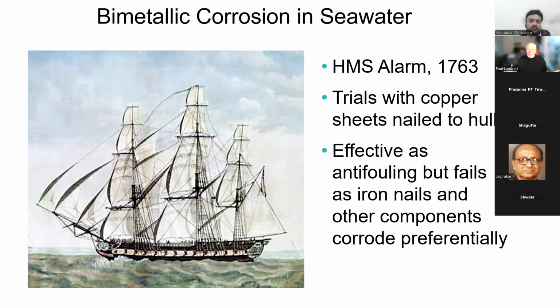Now, it was basically one of the first ships that they tried out with a copper bottom hull. So they got copper sheeting nailed to the hull. They initially used iron nails, but very quickly realized that was a bad idea. As you start to understand how mixing different metals can work, you've got small areas of very corrodable metal linked electrically and in a continuous electrolyte with a huge area of a less corrodable metal, or indeed a noble metal and a base metal, the base nails and the noble copper. That comes from Humphrey Davy. He first put the order in and called them base, where they were most likely to corrode, and noble, where they were least likely to corrode. But they noticed this in 1763, very quickly observed that this was a problem.